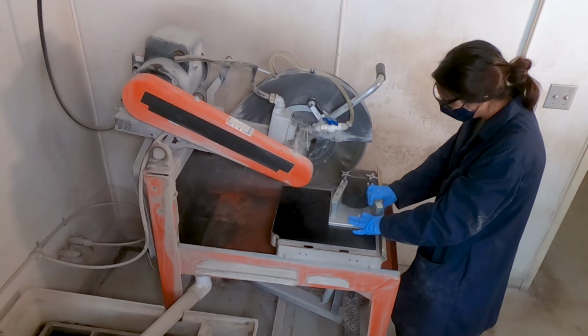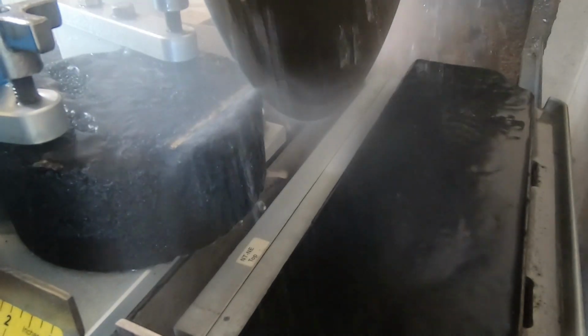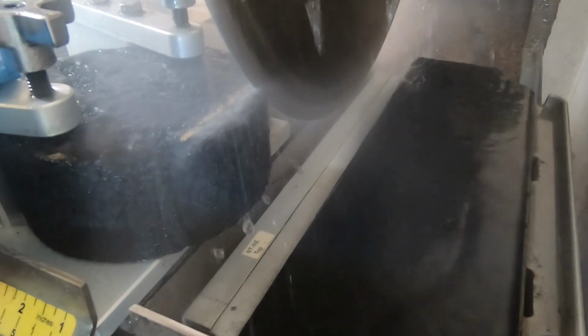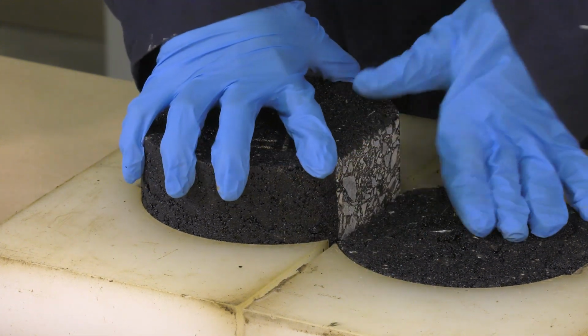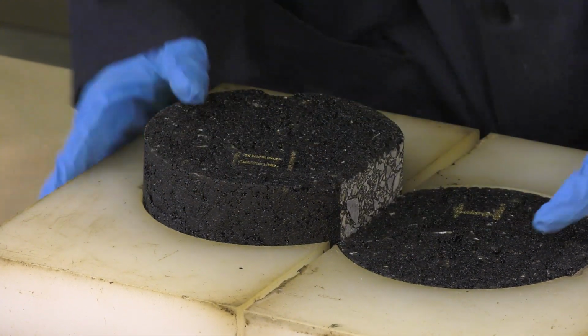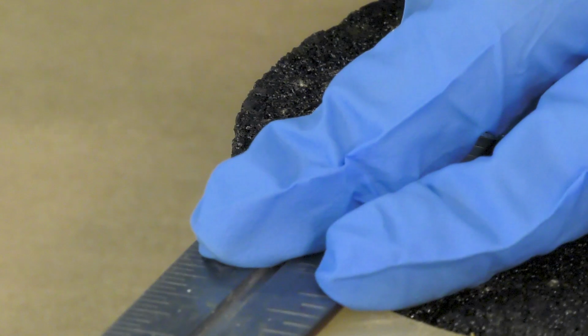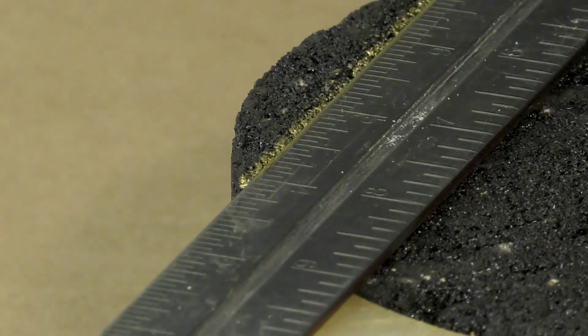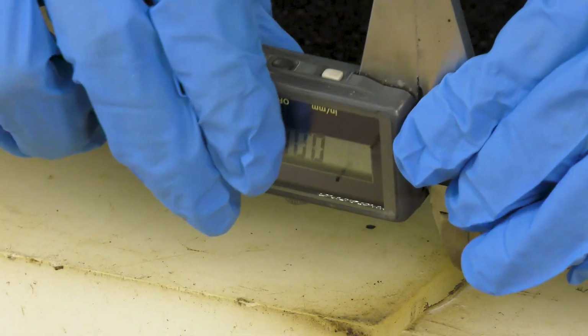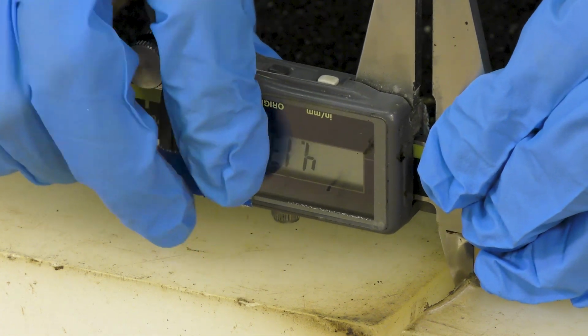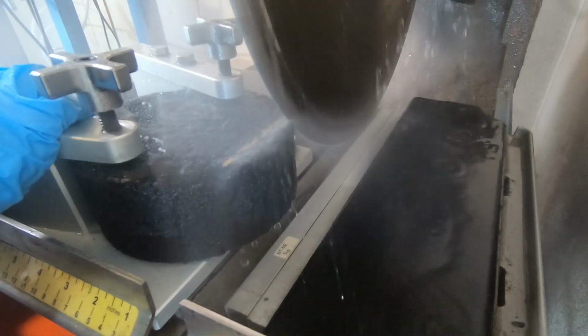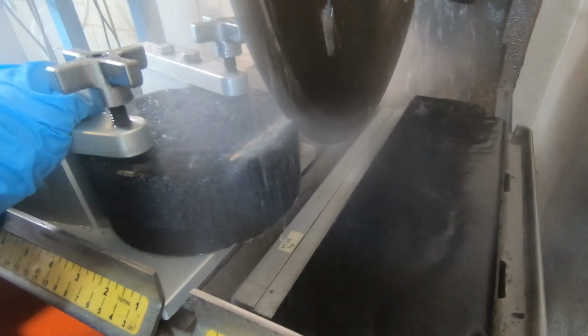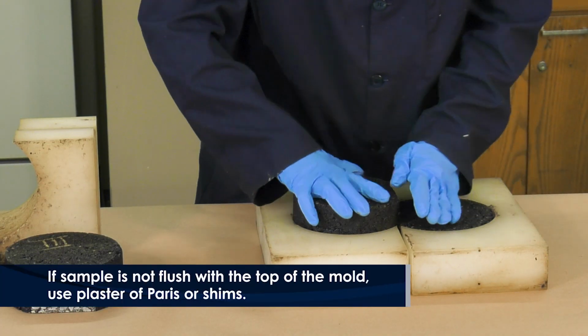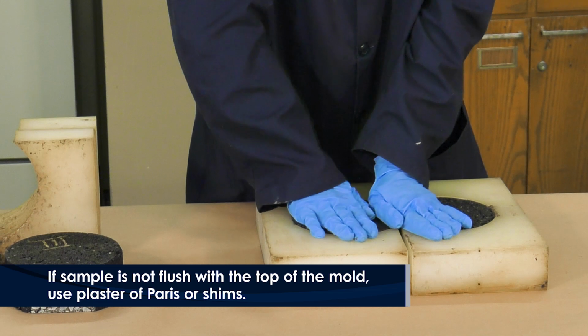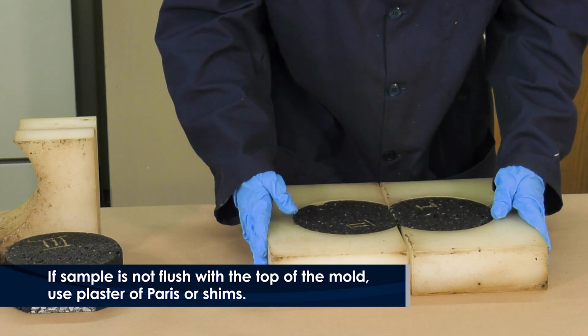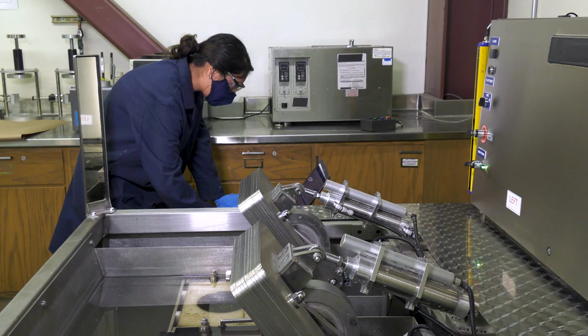Cut the specimens using a wet saw along equal secant lines or chords such that when joined together in the molds, there is no space between the cut edges. The amount of material sawed from the SGC cylindrical specimens may vary to achieve a gap width no greater than 7.5 mm between the molds. Consistent cutting may involve the use of a jig. Secure the test specimens in the mounting tray in such a way that the top of the specimen is level with the top surface of the HDPE molds.